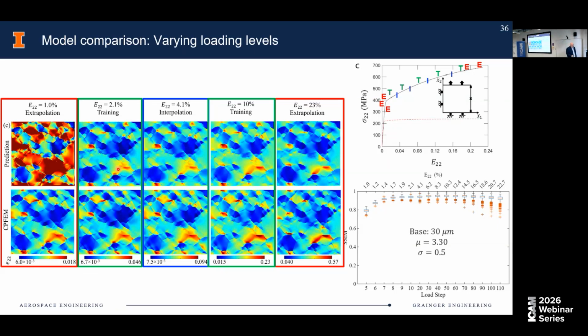Can we extrapolate? Not as good, although extrapolating to higher strains worked a little bit. You can see this in this sort of box and whisker plot, right? So the boxes are the 25 to 75 percentile. And there, again, this is the SSIM. It should be 1. It maintains pretty good values, even for extrapolated strains. Where it loses it is for smaller strains. Well, that's where the thing becomes elastic. Right? This is crystal plasticity. So that kind of makes sense.